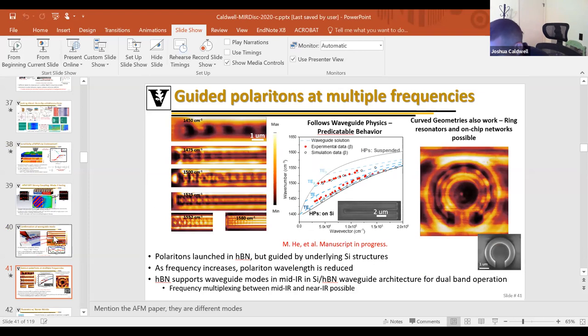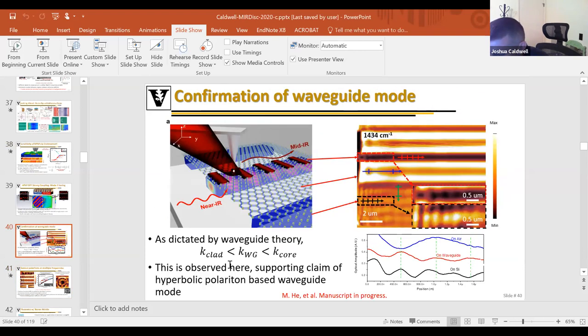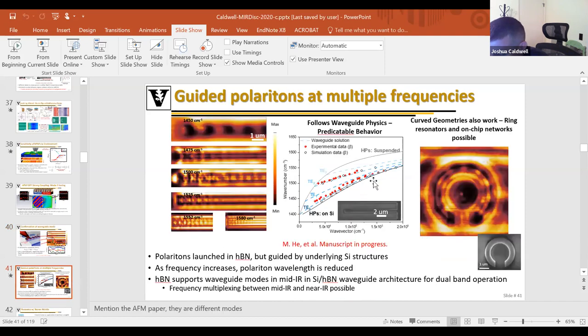I didn't talk about it too much, but effectively in this case, your core is the boron nitride over the silicon, whereas your cladding is the boron nitride over a suspended area. And just like a waveguide, you find a polaritonic wavelength that falls between the bulk polariton on air and the bulk polariton on silicon. That dispersion transitions depending on where you are in momentum space. Hopefully that answered the question. If not, please feel free to ask again.